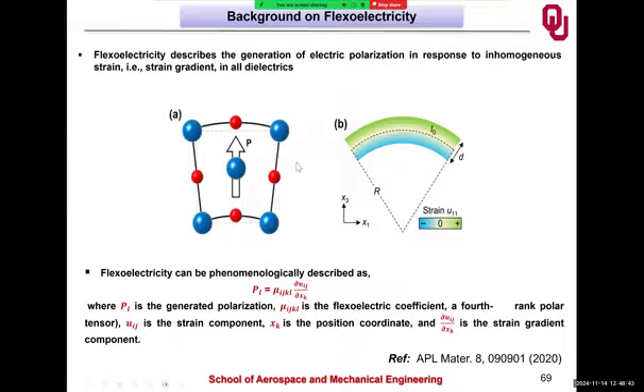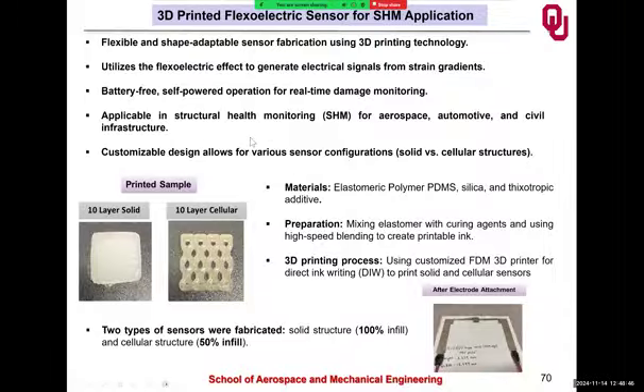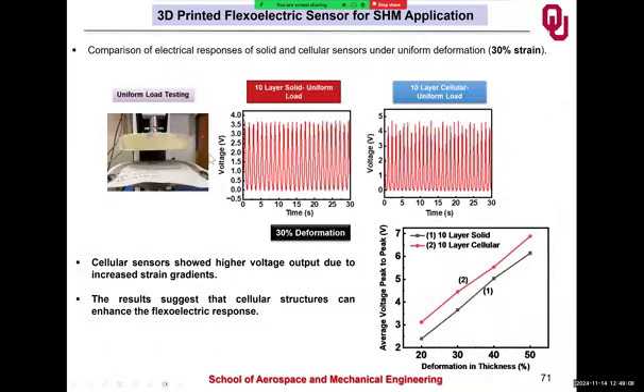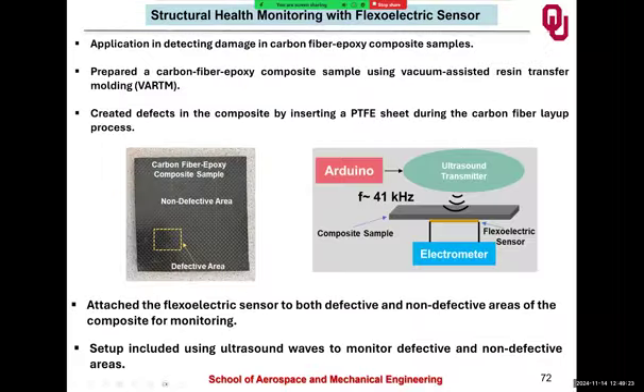By using this phenomenon, we printed the flexoelectric sensor, and here are some examples. We printed two types of sensors, one 100% solid and one with 50% infill, using a very simple material, the elastomeric polymer PDMS. Here we tested our sensor with mechanical testing under uniform load, and we see that the 50% cellular sensor gives a higher response. So later, we used that cellular sensor in our structural health monitoring application.